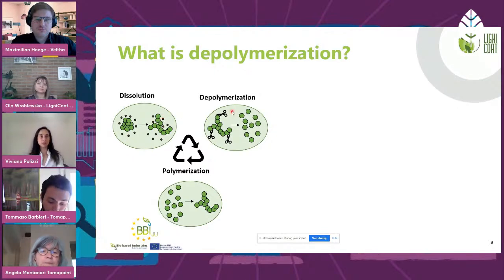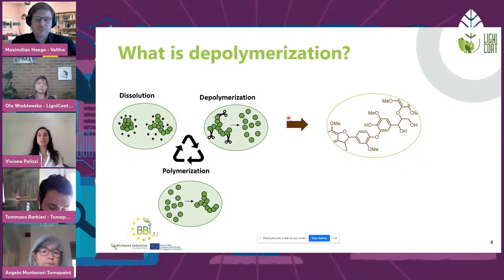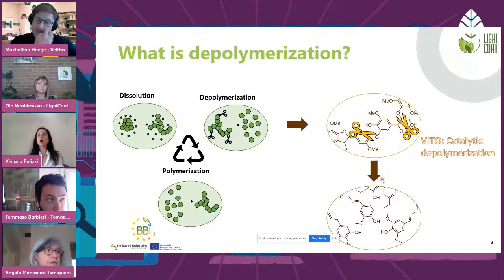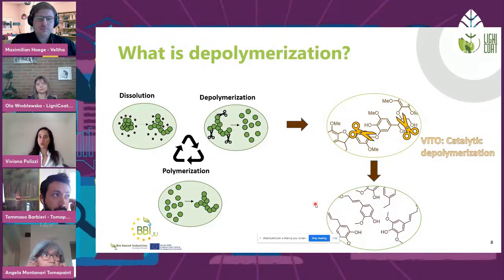The second step will be depolymerization, which means that the lignin structure is cut at different points, so different bonds are cut to obtain lignin fractions or depolymerized lignin, which range from monomeric to oligomeric structures. These mixtures can be used as such or after chemical modification or after further fractionation to be used in synthesis of biopolymers. So all the expertise concerning these steps is present in our group.